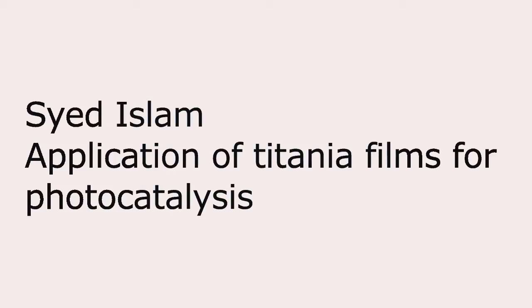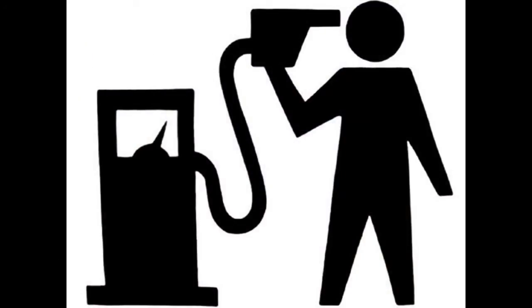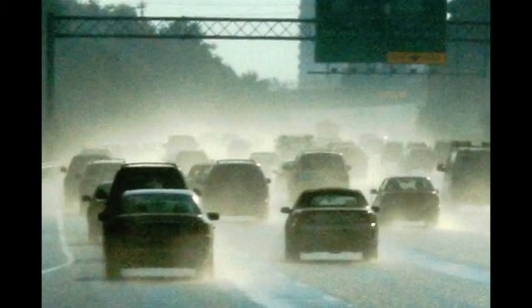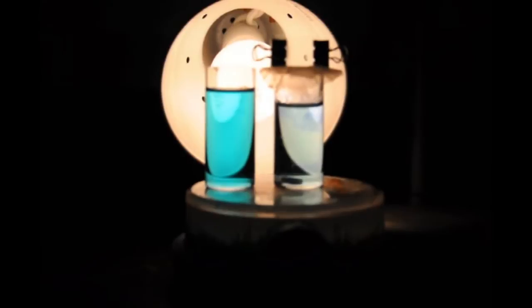Hi, I am Syed. I am working in the application of titania film for solar energy conversion. Increasing energy needs, decreasing fossil fuel resources, and environmental concerns of CO2 emissions is driving the search for clean and renewable energy. Utilization of solar energy is considered the ultimate solution. Surfactant-templated mesoporous nitrogen-doped titania thin films can be used as a photocatalyst for carbon dioxide reduction and hydrocarbon fuel production. This is a nitrogen-doped titania film and this is an environmentally detrimental methylene blue solution. These titania films decompose this methylene blue solution into colorless forms.